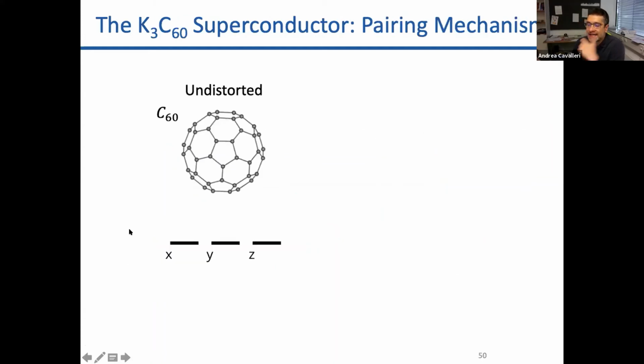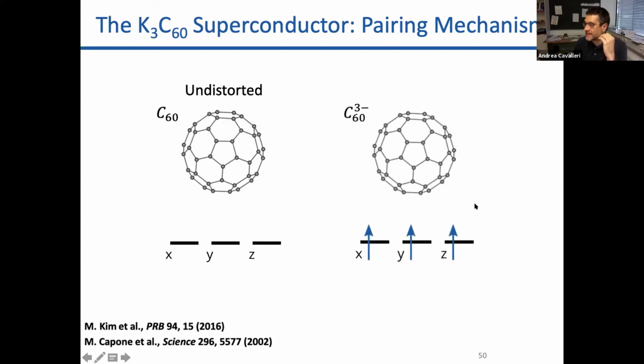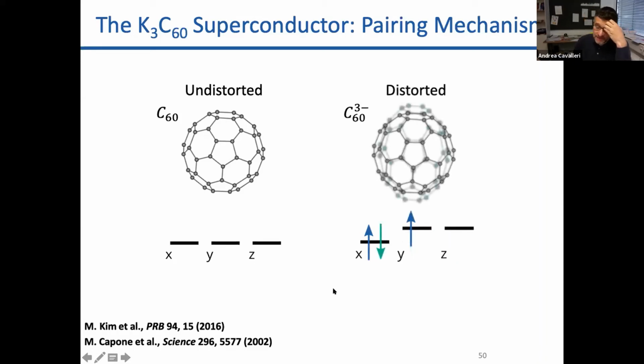And the reason why this material becomes superconducting is the following. Let's think about an individual C60 molecule. This is the undistorted molecule. These are 3 degenerate orbitals, which are the lowest unoccupied molecular orbital, which I'm now doping 3 times, as I said, because of the presence of the potassium atoms. And now, without anything else, one might expect a high spin state because of Hund's rule coupling, except that this molecule is unstable against a lattice Jahn-Teller distortion, by virtue of which the material acquires a low spin state.